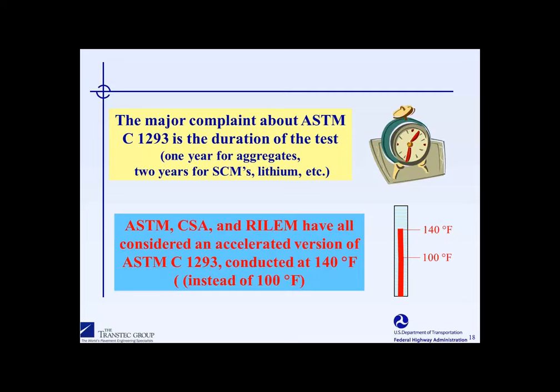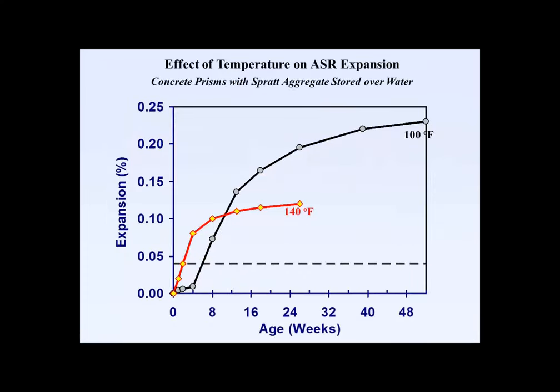Unfortunately, the data that has been generated over the last 10 years is not very promising with regard to this accelerated test. The primary reason is that we get considerably less expansion at higher temperatures than we do when we test at the standard 100 degree Fahrenheit temperature. Somewhere in the range of a 30 to 50% reduction in expansion when we increase the temperature. Now that probably seems counterintuitive, because ASR is a chemical reaction, and chemical reactions are accelerated or increased through temperature.